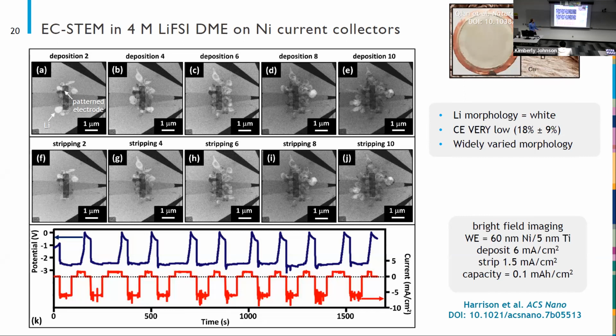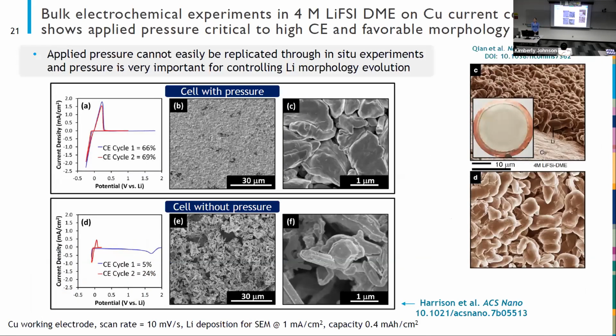So we are able to get realistic electrochemical curves, but this is kind of baffling because we were expecting to get the nice morphology and the high coulombic efficiency in the Nature Communications paper that I introduced earlier. So we thought a lot about what the various things are that are different in our TEM experiment versus a coin cell, because clearly we weren't replicating something correctly. And the most important thing that we thought to look at first was the effects of applied pressure. In a coin cell, we have pressure on the interfaces, and so all of that electrochemistry is taking place under pressure. In the TEM cell, we really can't do that because the place where we're imaging is thin and delicate, and we can't put pressure on it and still be able to image at the same time.